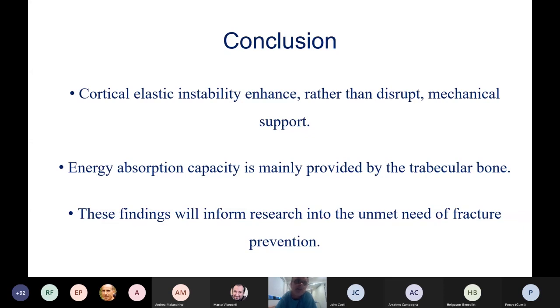support was provided, reaching some strain level inside the trabecular bone that exceeds typical failure strains seen in normal small bone core testing. So energy absorption capacity is mainly provided by the trabecular bone, because that's where we have seen the bigger deformation, particularly starting from the subchondral bone, where the high deformation happens right from the very early loading. I think that these are important findings that put another view to the femur fracture behavior as compared to the theory of elastic instability. And so this type of behavior can be used to meet the unmet need of fracture prevention, so developing a better fracture model for bone.